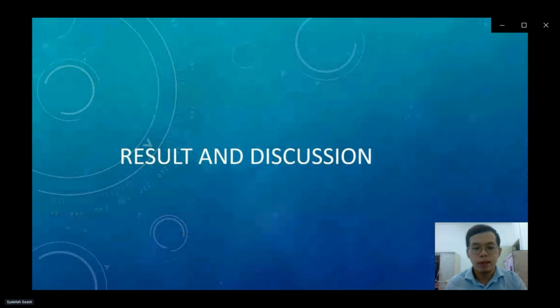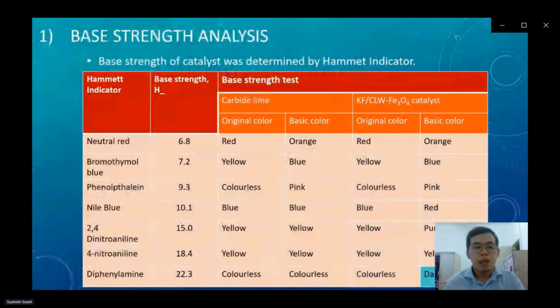Then I would like to present the results and the discussion from this project. First is the base strength analysis. The base strength of the catalyst was determined by the Hammett indicator. As you can see, the base strength of the carbide lime is up to phenolphthalein. The base strength is 9.3. The original color of the phenolphthalein changed from colorless to pink. While for the KF/CLW/Fe3O4, it falls under diphenylamine, for which the base strength is 22.3. The diphenylamine changed from colorless to dark blue. So it means the KF/CLW/Fe3O4 has a base strength of 22.3.